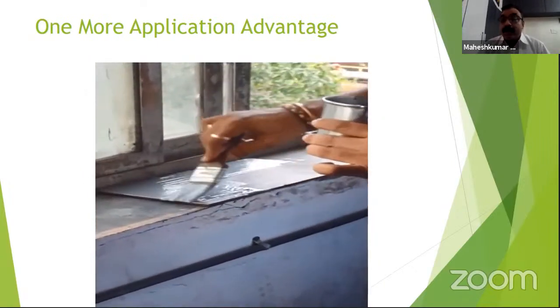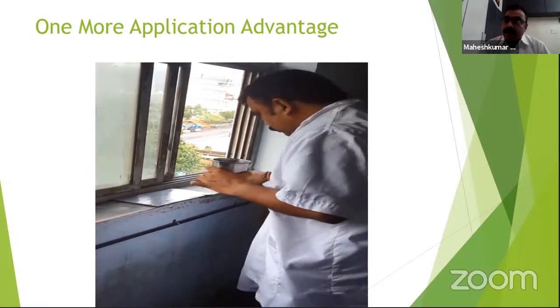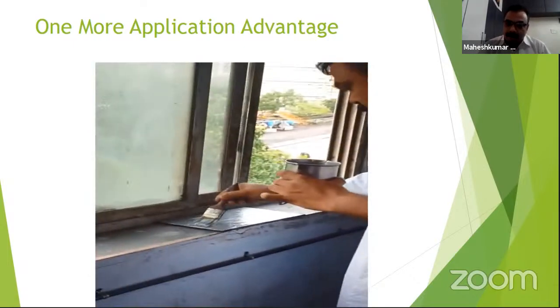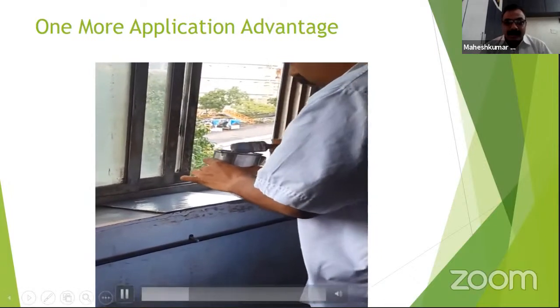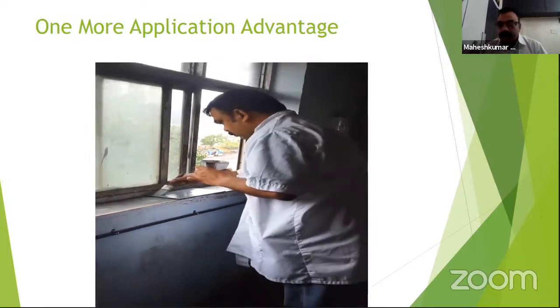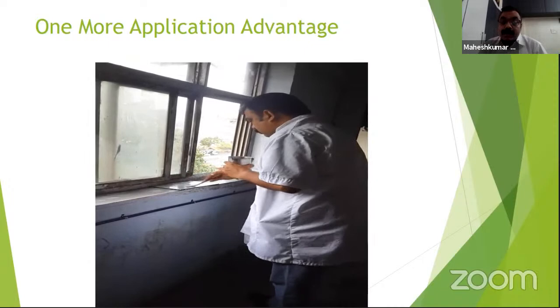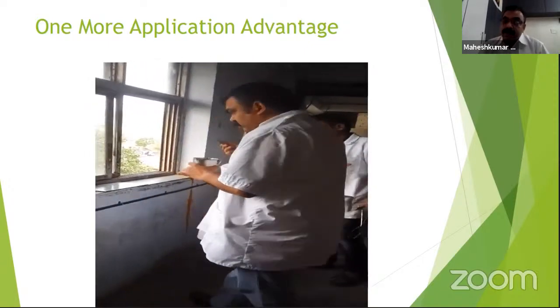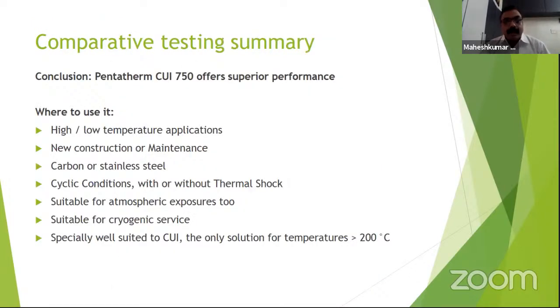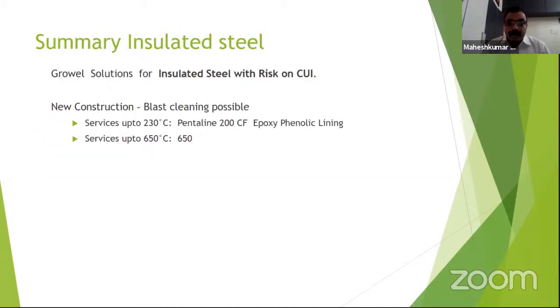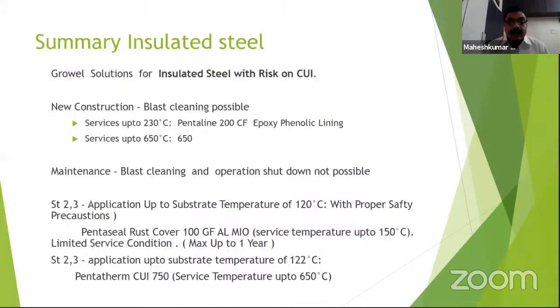This CUI coating you can apply onto temperatures up to 100 degrees C easily. You can see some fumes there, but these are not poisonous material. It is the smell of those solvents, which are very, very slow evaporating. And all the tests were performed, and what we found is that if blast cleaning is possible, service temperature up to the limit with our CUI, that is phenolic lining, is possible, and for services above this we have to go only and only with systems which are going to give you a higher degree of corrosion resistance.